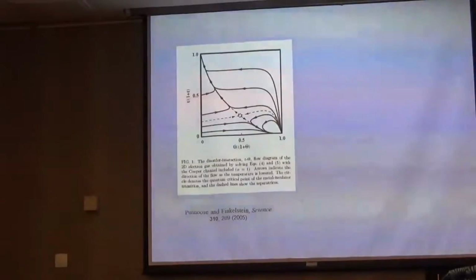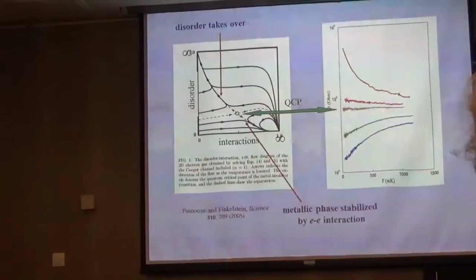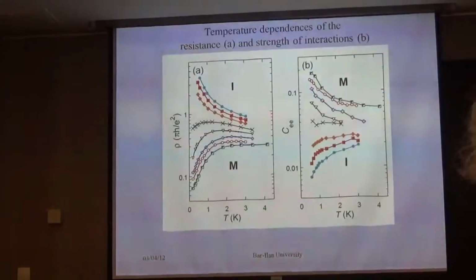If it is too strong, resistance first grows when temperature is going down and then keeps increasing, and the resistance goes to infinity. But between those two regimes there is a quantum critical point, which probably corresponds to this flat curve in our data. Quantum critical point means that the temperature goes to zero and we end up at this point. Resistance, disorder, interactions, nothing changes once we end up at this point. And indeed, we change the temperature here by a factor of 30 or 40, and nothing happens. Resistance just remains constant.